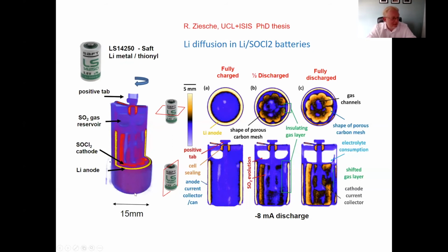But this is actually a three-dimensional tomography image of a commercially available lithium battery. And so 53 tomography images were taken of this battery. And here you can see a three-dimensional reconstruction of the inside of the battery. And here you can see slices through that battery at different stages of charging and discharging. So here it is fully charged, here it is half charged, and here it is fully discharged.